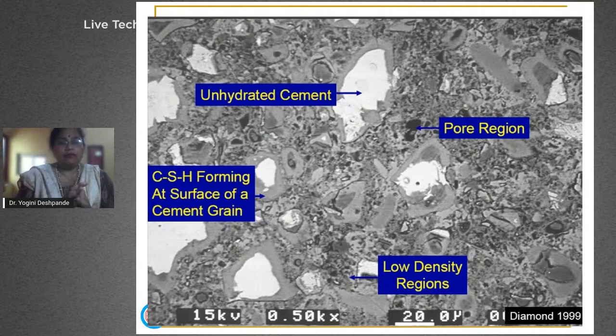One key takeaway is that cement doesn't necessarily completely hydrate when the concrete is hardened. Some amount of cement particles continue to remain in an unhydrated stage over time, and this is utilized in certain waterproofing chemicals or bacterial concrete that is being developed. The idea is that the unhydrated cement or any CH formed will react once a crack has happened, and CSH will form at that point, closing the crack again.